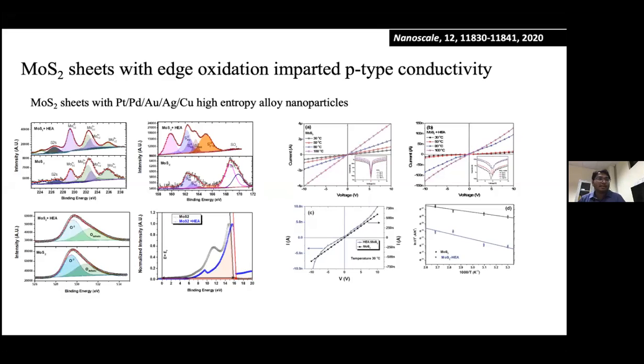So this is our recent work, which was done in collaboration with some of the people from IIT Kharagpur, IIT Kanpur, and IISc. And those metallurgists actually prepared high entropy alloys. These alloys are high entropy in the sense that they are a mix of various elements, and their configurational entropy is really high because they are disordered systems. So practically on a large scale, again, it is uniform. So these nanoparticles of around 4 to 5 nanometers were put onto these MoS2 sheets.